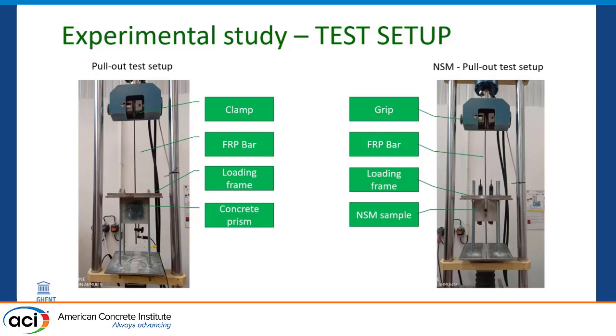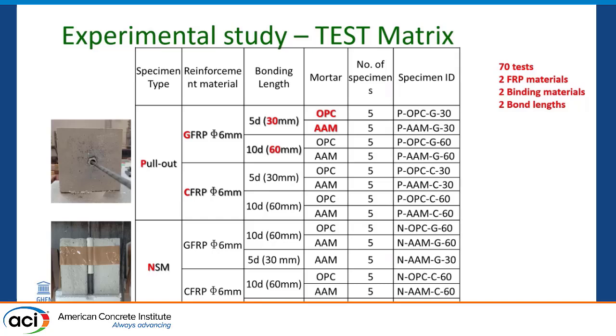So here you can see the test setup. There is the clamp, then the loading frame, and LVDT on the unloaded end of the rebar. The same is for near surface mounting. So we did in total 70 tests with 2 FRP materials, with 2 binding materials, and 2 bond lengths. We did 40 pull-out tests and 30 near surface mounted tests, because in pull-out tests we did GFRP with 6 millimeters with an embedment length of 5D for both OPC and AAMs, and for 10D the same. And in near surface mounting, we omitted 5D for Portland cement. We only tested 10D.